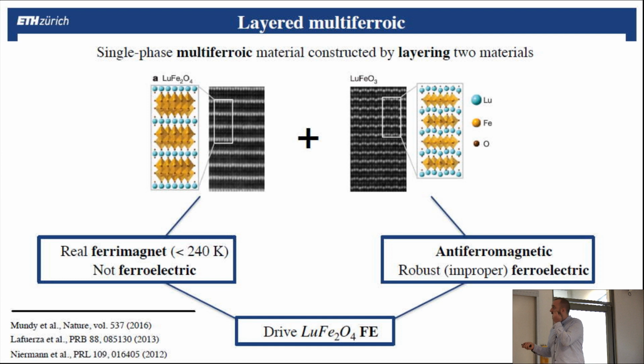And this was actually done, and it was the first time that people showed that one can engineer a multiferroic material not by changing A and B atoms, but by stacking together two types of material. To do that, they considered lutetium ferrite and lutetium iron oxide, LuFe2O4. And this material is ferrimagnetic, meaning antiferromagnetic, but with different amplitudes. So it has a net magnetization, but it's not ferroelectric. This material is antiferromagnetic, but ferroelectric.